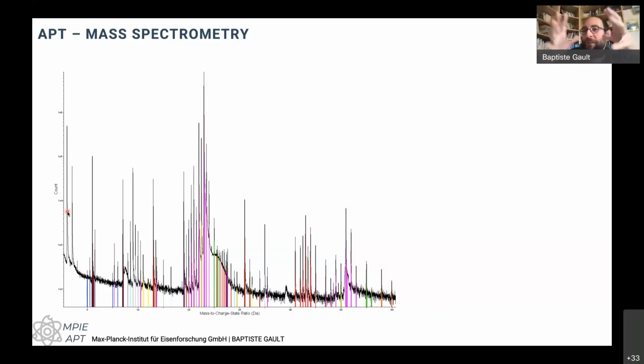There's some hydrogen adsorbed on the surface of the needle. So when we transport through air, even when we make needles inside of the FIB or electrochemically, we are going to introduce some hydrogen inside of the chamber. Detecting inside of the specimen. So detecting hydrogen is not hard. The problem is the interpretation of the data. So will the hydrogen actually be coming from inside the needle, inside the sample, or will it actually come from the chamber and be just a spurious species causing problems?